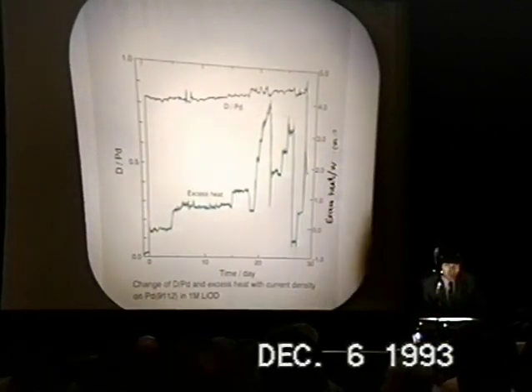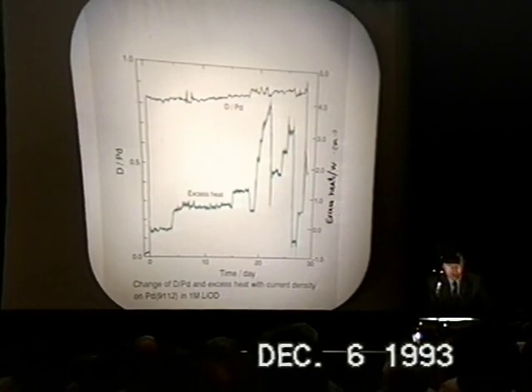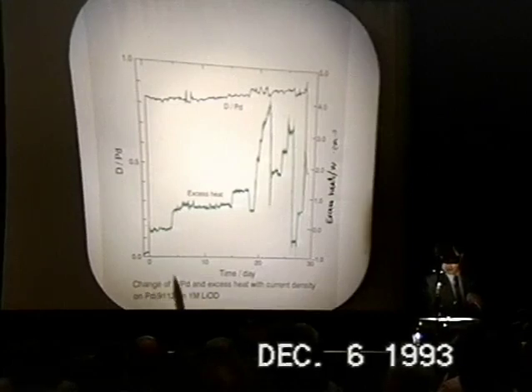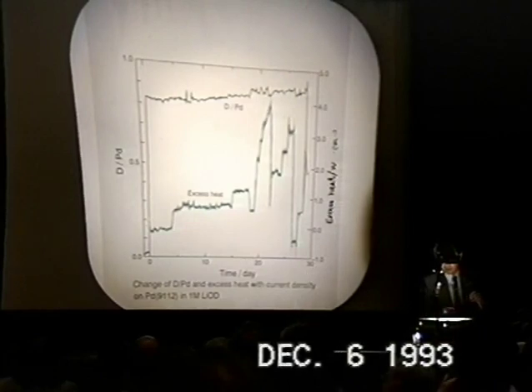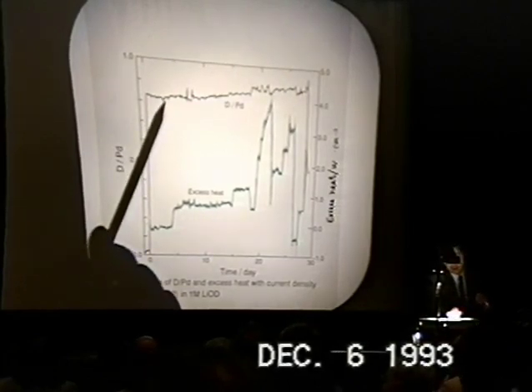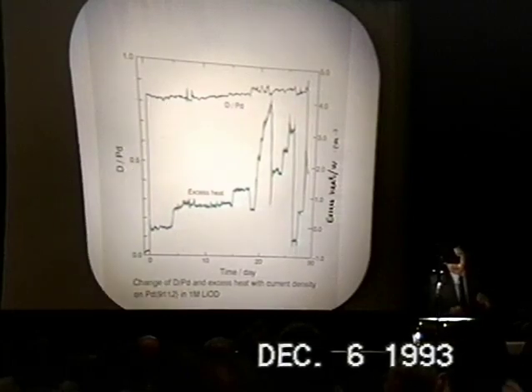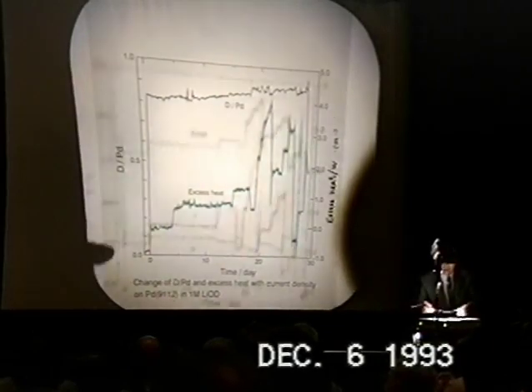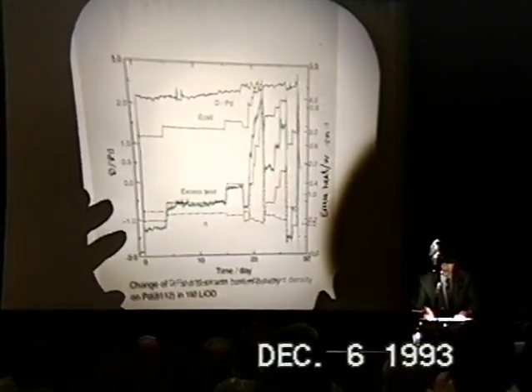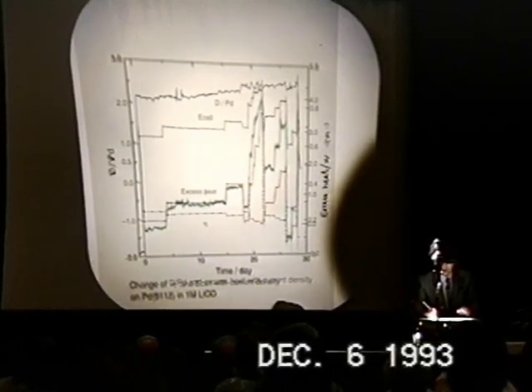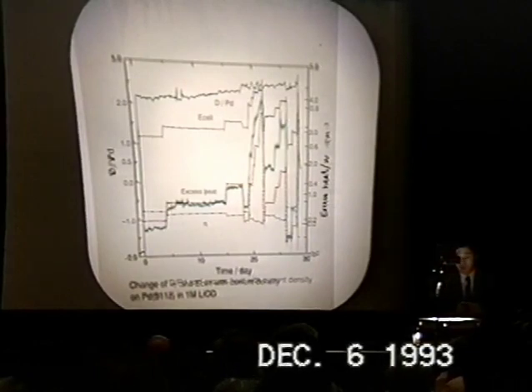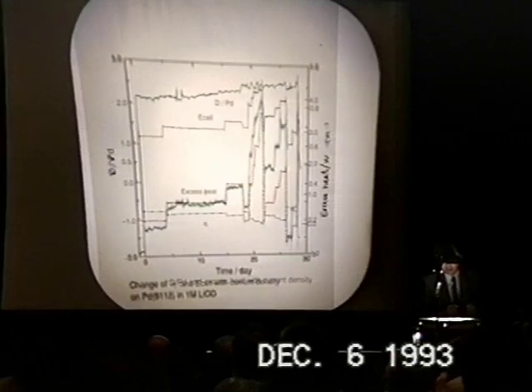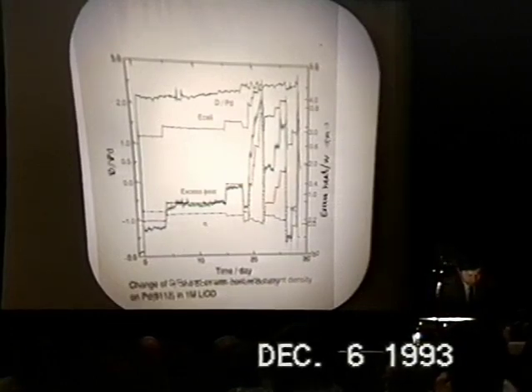And from these old data, we also know that this shows the excess heat, the change of excess heat along the time axis, which continued for nearly 30 days. And then we are showing the D/Pd at the top. But we superimpose this with the actual current applied during this period. We can see a very close correlation between the excess heat change and the current density change. Again, the current density and overvoltage is very well correlated in many ways.